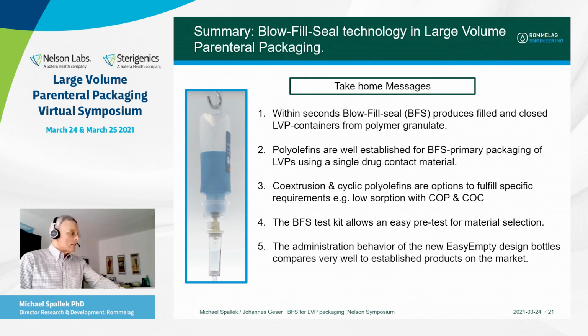For special applications, we can use co-extrusion and/or cyclic polyolefins, COCs, COPs, for example, for requirements on low adsorption to the inner surface. With our BFS test kit, we can have an easy pre-test for material selection, for compatibility testing, etc. And for our new easy empty bottle, the administration behavior nicely compares to established products on the market.